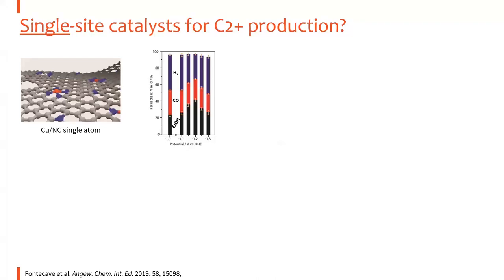So many of us know that single atom has been a hot topic in recent years. Single atom can find applications in a broader range of different reactions, including thermal reactions, bioreactions, and electrochemical catalysis, of course. One recent example is that some researchers in France have developed a copper-based single atom catalyst supported on nitrogen-doped carbon material. What they found is that beyond the single carbon product which single atom catalysts usually generate, they identified quite a number of ethanol in their products. So we know ethanol is a C2 product, CH3CH2OH. So it's a multi-carbon product.